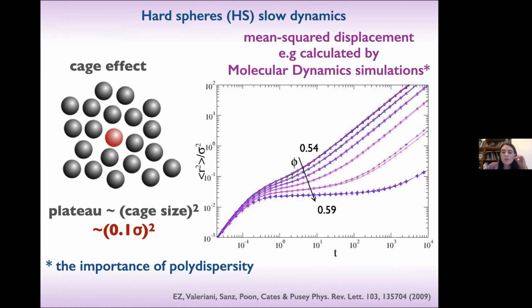One thing that I want to stress, which will be important in the following, is that the height of this plateau for the hard-sphere glass transition is basically always the same and is roughly 0.1 of sigma, where sigma is the size of the particle, so 10%. So before becoming a glass, the particle can usually explore 10% of its diameter in the cage.